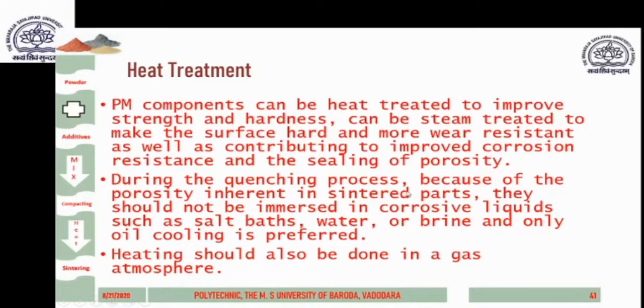During the quenching process, because of porosity inherent in sintered parts, they should not be immersed into corrosive liquids such as salt bath water or brine, and only oil cooling is preferred.